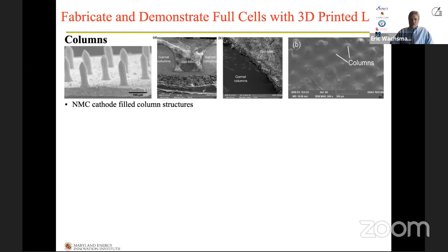Again, you can see the columns to the left, the photograph just to the right of that shows you the garnet columns on that bilayer structure, and then the NMC cathode, which is mixed with a gel in the pore space between the columns. There's a magnification of that to the right of that. And then the figure to the far right is just looking down on this. You can see the bumps sticking up from each of the columns as we fill this with this NMC cathode material.